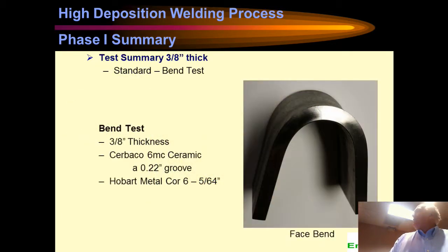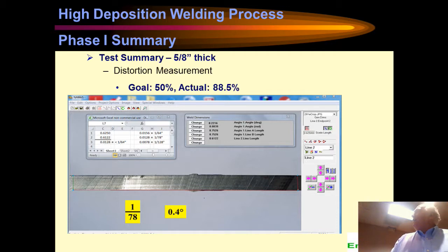Bend tests went fine, and then I get to the distortion, and so we did distortion measurement here on the 5/8 material. Over 8.9 inches, we got 1/78 of an inch of deflection. So it's pretty much as close to flat.